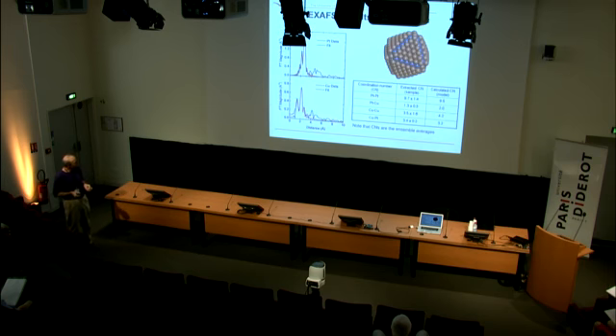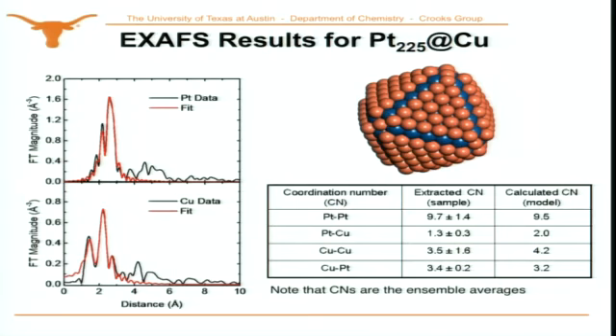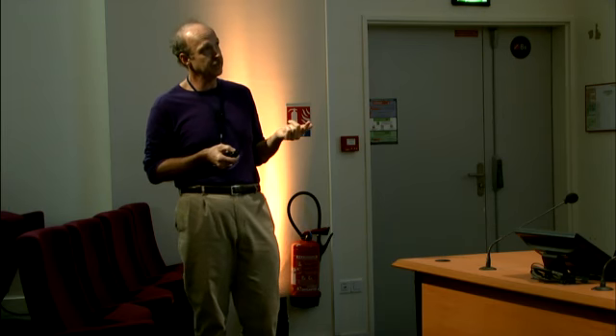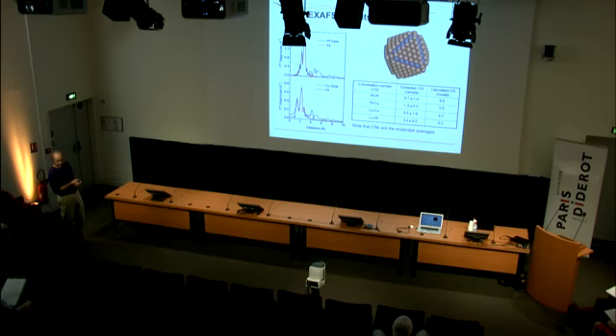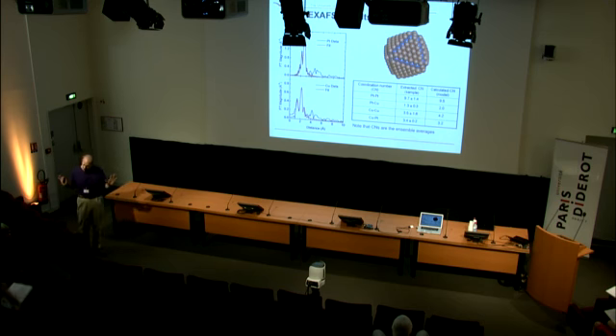It takes about 2 hours to collect enough data to get the signal to noise to a reasonable level. So here's what the data look like. The black data here are collected from the platinum edge, and the black data down here are from the copper edge. To analyze XAFS data, one simulates using software called Ifeffit, which almost everybody uses, I think. So everyone's agreed. If we're lying, we're all telling the same lie, okay? But this is what everybody does.